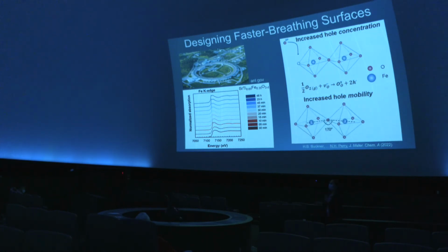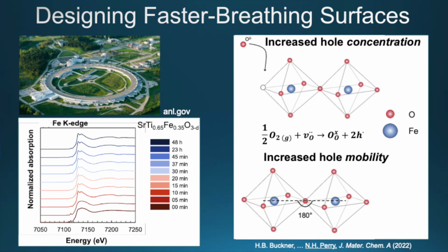This is a different technique now called X-ray absorption spectroscopy. We're firing these high energy X-rays at our material and getting information about how they absorb them, about the local chemistry at the atomic scale in the materials. And it tells us how it's evolving, and it helps us to understand why charge is now moving really quickly through these materials. One of the reasons is that as oxygen comes in, as they crystallize, we're creating something called holes. And these are like the positive version of electrons. Okay, they're charges, we're creating them in the material. And the other thing that we learn from the structural changes is that these atoms are becoming better aligned during this process. And that helps these holes move through the material really, really quickly.